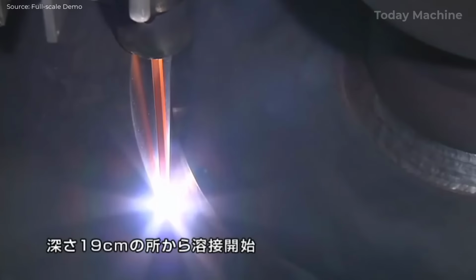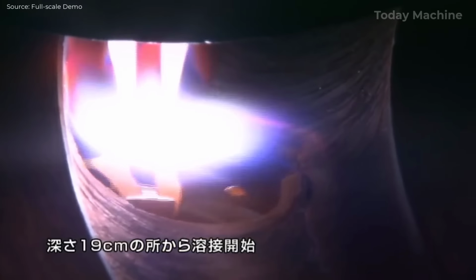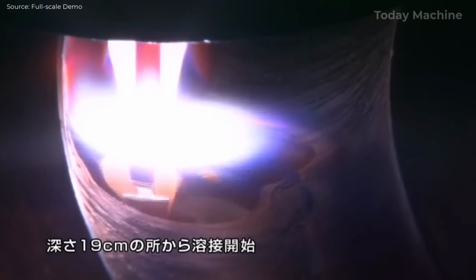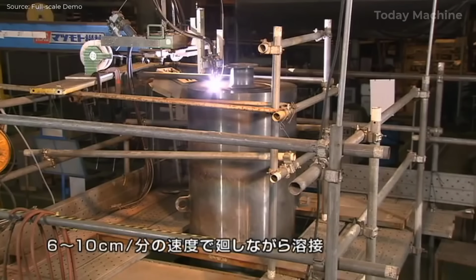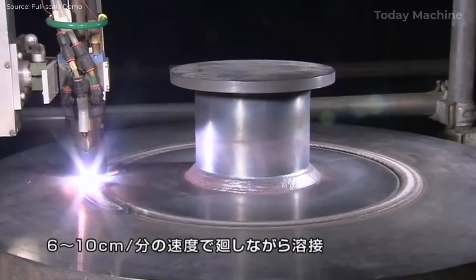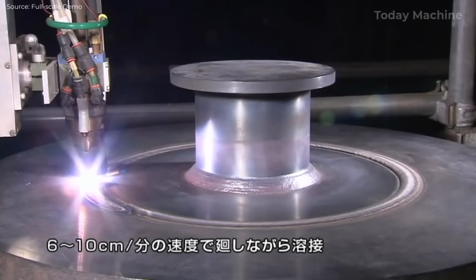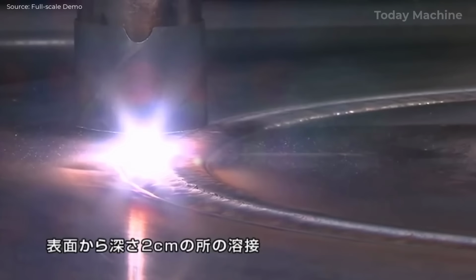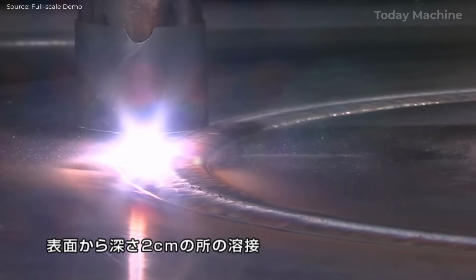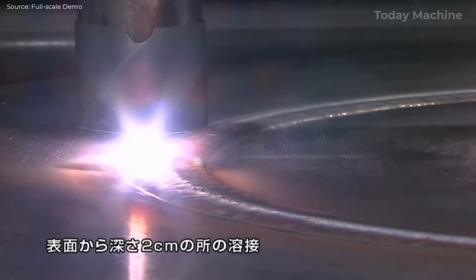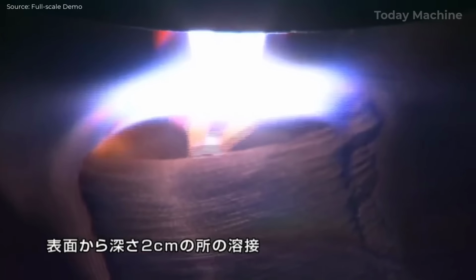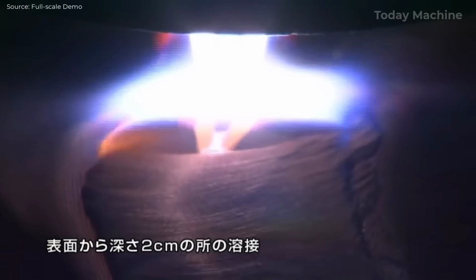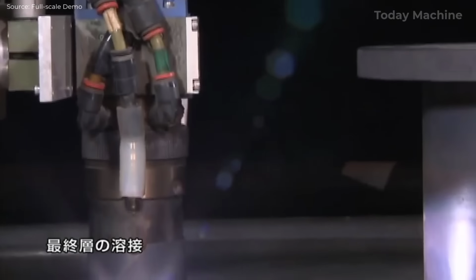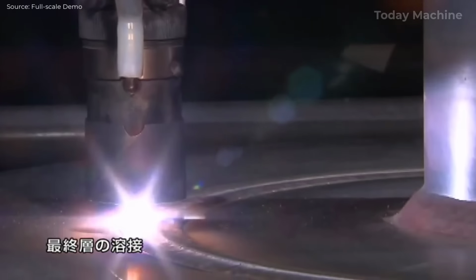The body and lid are welded together using TIG, tungsten inert gas, welding, a process known for its precision and strong welds. The welding begins at a depth of 19 centimeters from the surface and proceeds at a speed of 6 to 10 centimeters per minute, ensuring a controlled and consistent weld. The welding process is conducted in multiple layers, starting with the deeper layers and gradually moving towards the surface. The final welding layer is completed at a depth of 2 centimeters from the surface, ensuring that the entire weld is robust and secure.